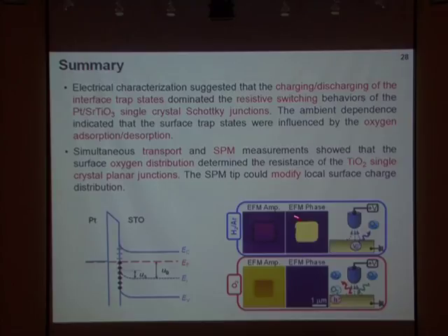In the latter part, I showed some AFM studies. In this case, oxygen distribution is also really important in determining resistance states. And also, we can learn that SPM tip is really a powerful tool to modify the local surface charge distribution.